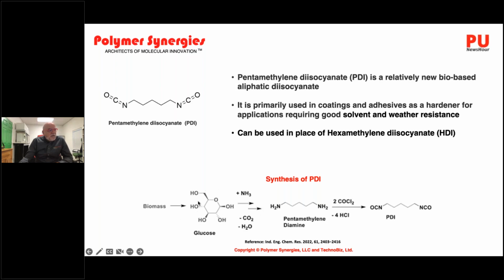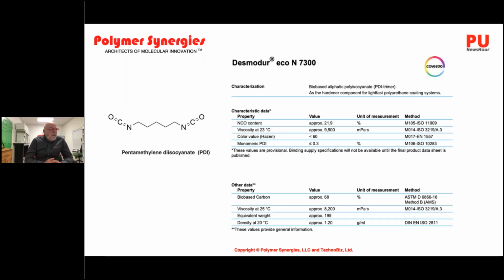It's made from biomass, so it starts with the glucose from biomass. It goes through a amination process and phosgenation to form the pentamethylene diisocyanate. This is a technical data sheet of Desmodur Eco N7300. It is their version of pentamethylene diisocyanate. And you can see that it's got an NCO of approximately 22%. Its viscosity is fairly high, 9,500. And its bio-based content is approximately 68%. So pentamethylene diisocyanate is available from Covestro. It's also available from other sources that you can find from polyol suppliers.